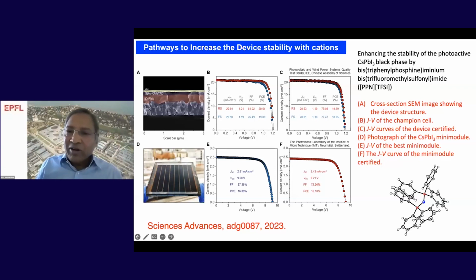So we have come up with a modified ionic liquid. The structure is shown below, the crystal structure of the ionic liquid. And the name of the ionic liquid is bis(triphenylphosphine)iminium bis(trifluoromethylsulfonyl)imide. By combining this ionic liquid with cesium lead iodide perovskite, you can stabilize it in the alpha phase. This work appeared in the beginning of this year in Science Advances.